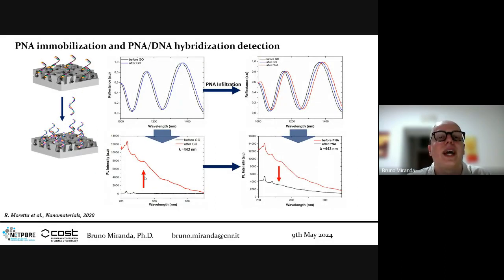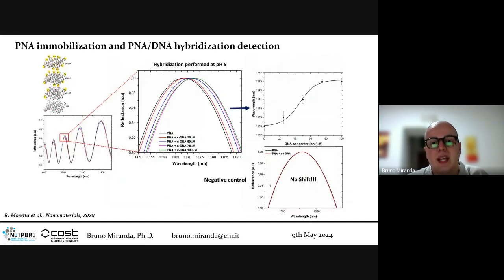Then we have the PNA-DNA hybridization. After GO, we have PNA, and we see a further red shift in the reflectance spectrum. What's important here is the quenching of the photoluminescence of graphene oxide due to the presence of PNA. Finally, we have DNA hybridization with different concentrations.